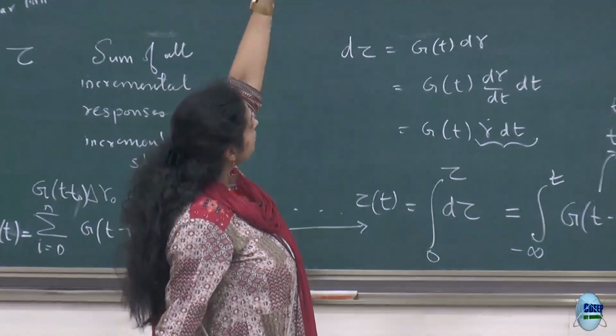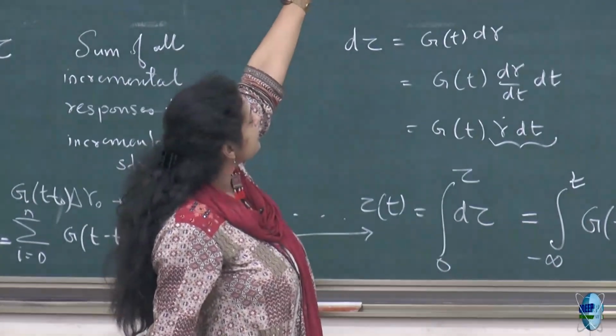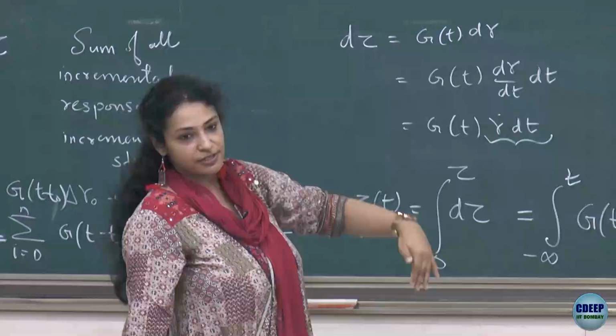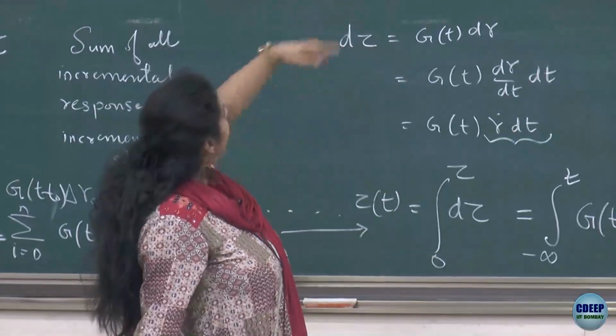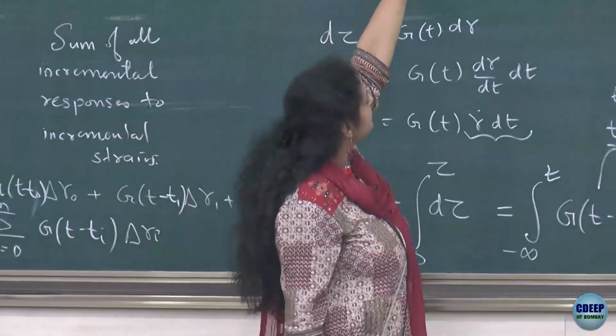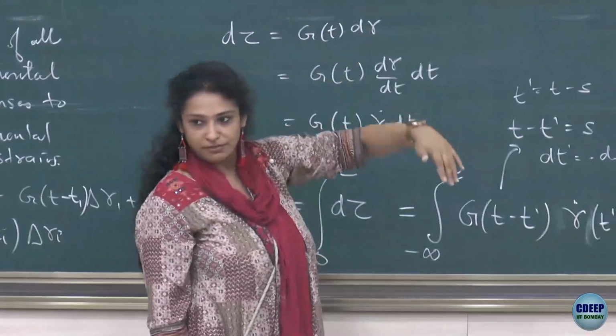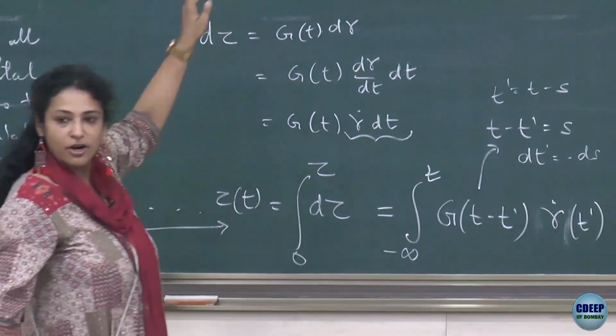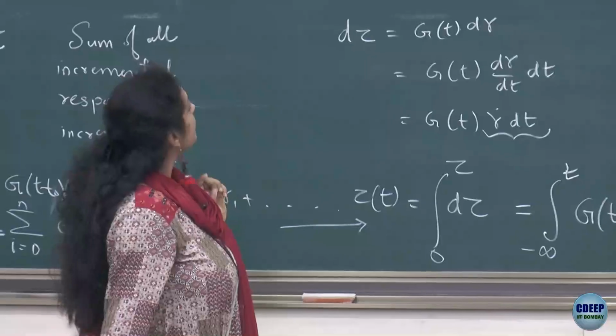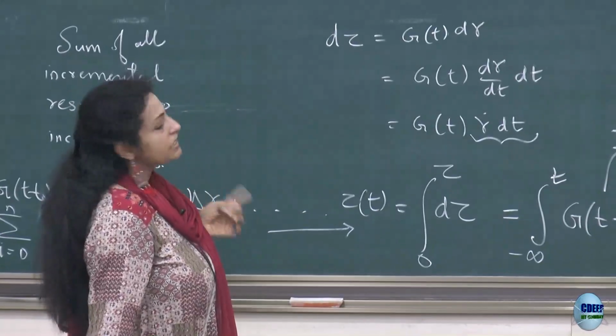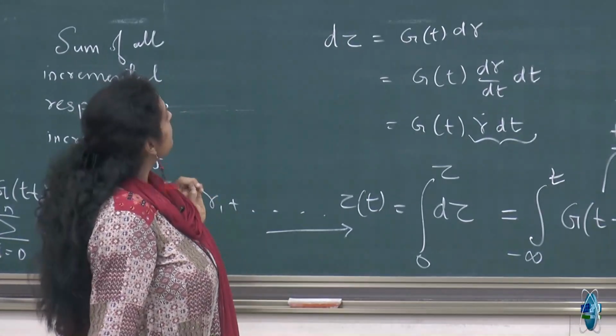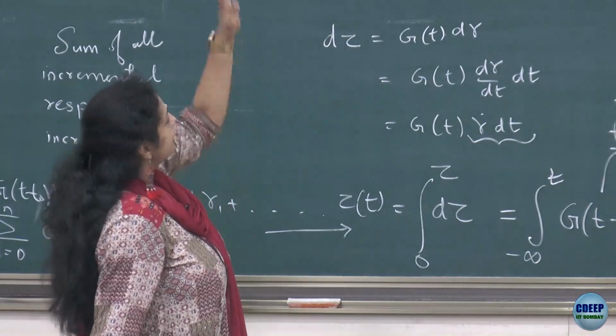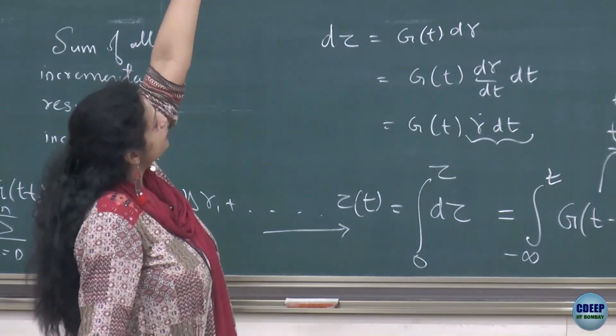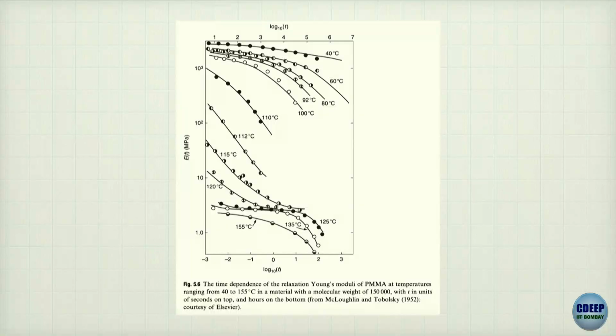So at the very top, you can see around 100 degrees, 110 degrees, you are seeing some sort of a decay showing. Further at higher temperatures, again you are seeing that kind of a shape showing up. This is log of modulus versus log of time. This is for PMMA, PMMA melt at different temperatures. So you have the lowest temperature, 40 degrees Celsius, all the way to 155 degrees Celsius.